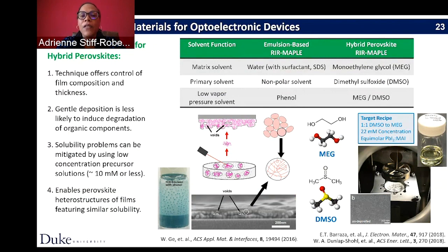And in finding the new matrix, because of all the work we've done with the polymer films, we knew what the functions of that matrix needed to be. We need something with multiple OH bonds, at least more than one, and we need something that has a low vapor pressure, again, to protect the integrity of the target during the vacuum process. So what we figured out was that we could make co-solvents for our solutions. So basically you have a primary solvent for the perovskite, something like dimethyl sulfoxide, DMSO, which is typically used for these materials. And then we use polyalcohols for the matrix. So something like monoethylene glycol, it has more than one OH bond, it has a low vapor pressure, and works very well for the MAPLE process.